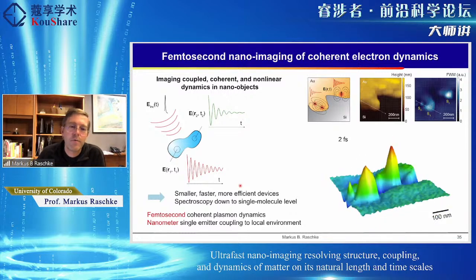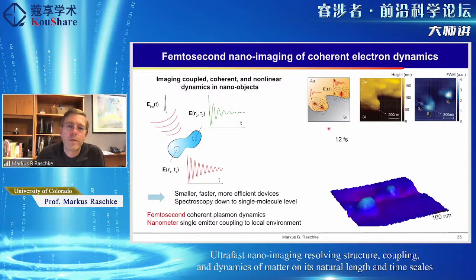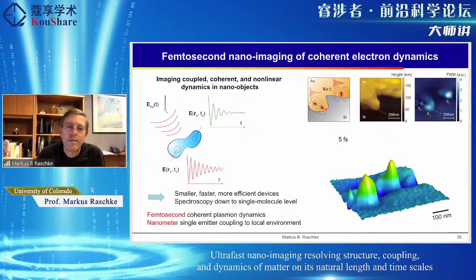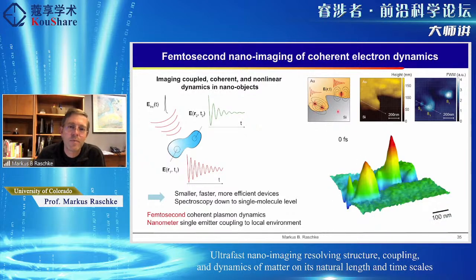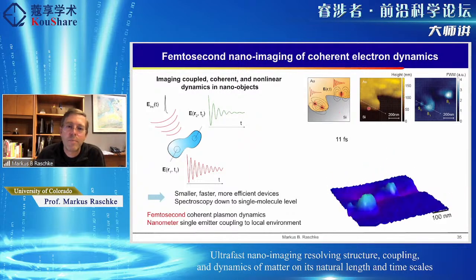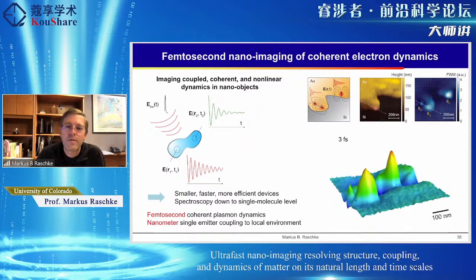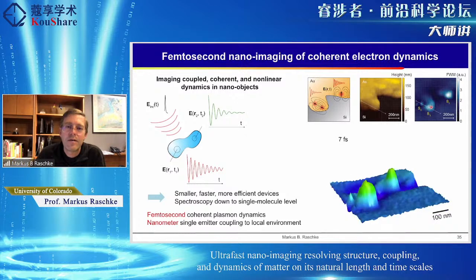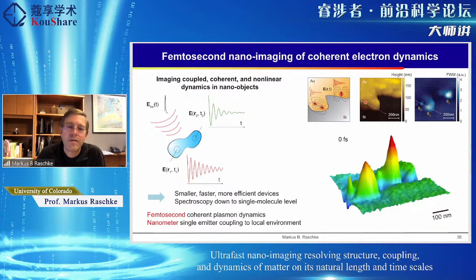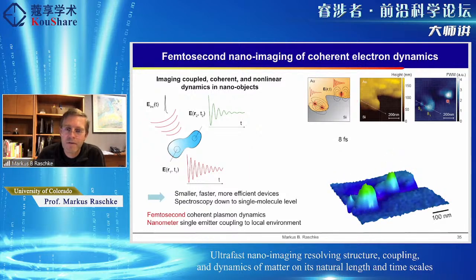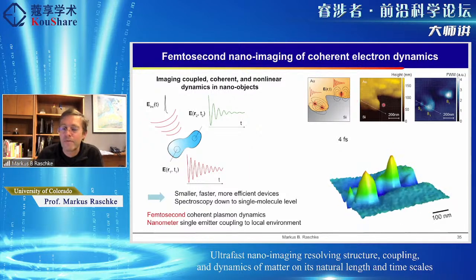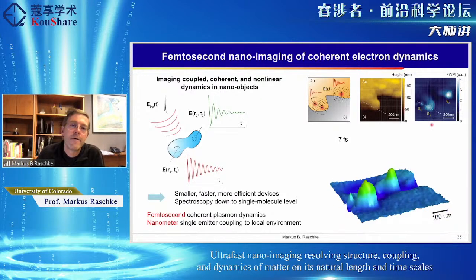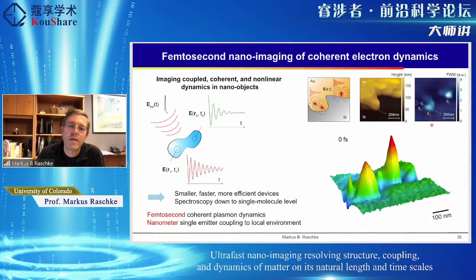And so here is how we establish this principle, where we do a very simple experiment. In practice, still difficult, but in the sample system, simple. It's an edge of a polycrystalline gold metal film, where within the bandwidths, we are exciting localized surface plasmons. And you see then the four-wave mixing signature of these. And then they interact and they decay. And this decay of this electronic coherence is determined by the Drude relaxation time, which is very fast because of the high carrier density.